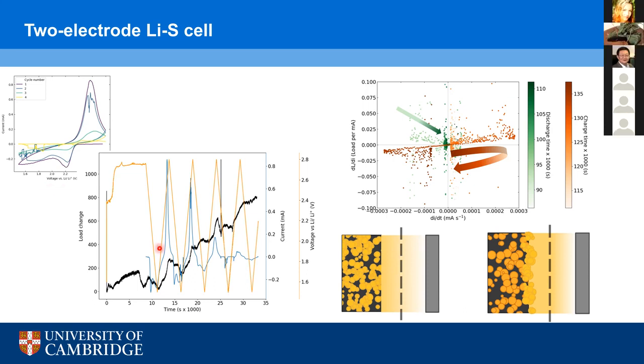So during the first 24 hours, which is represented by the part where there's a high voltage that's constant, this is where the cell was left so that the electrolyte could percolate through the separator and through the electrode as well. And there's a steady increase in pressure throughout this time, which is probably associated with the absorption and the swelling of the electrode by the electrolyte, and especially the polymer binder. Beyond this point where the voltage was then varied, there's a steady increase in the pressure with time, and also some more localized increases and decreases in pressure as the current changes.